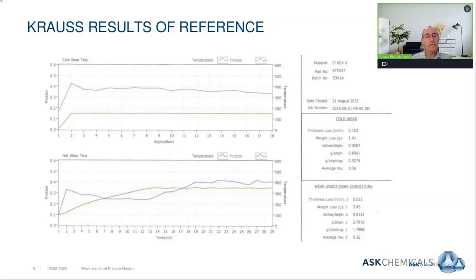This kind of behavior of initial green fade followed by over recovery, of course, is not ideal. One would prefer that the trend at higher temperature should resemble, to at least within about 10%, the curve at lower temperature. Now let's look at the wear behavior of this older technology.